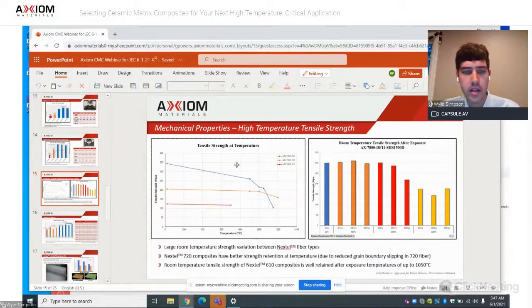So here are those tensile properties at temperature. You can see here, as that temperature gets to around 1,000 to 1,100 degrees Celsius, the 610 properties start to lower a little bit, whereas the 720 has more strength retention at those temperatures due to reduced grain boundary slipping in the 720 fiber. Here's a study we did on room temperature tensile strength retention on the 610 fiber after numerous cycles at various temperatures.